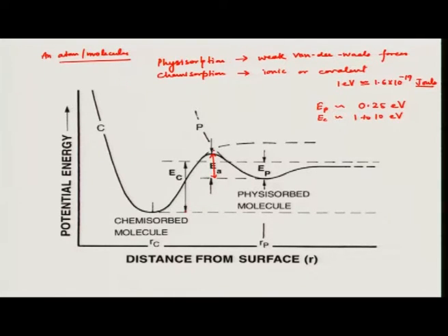It can be either by substrate heating or some chemical reaction. So, this activation energy has to be provided so that this atom or molecule goes from physisorbed state to a chemisorbed state, which will be much more stable because of ionic or covalent bonding between the surface and the atom or molecule. So, this is the process in which this happens.